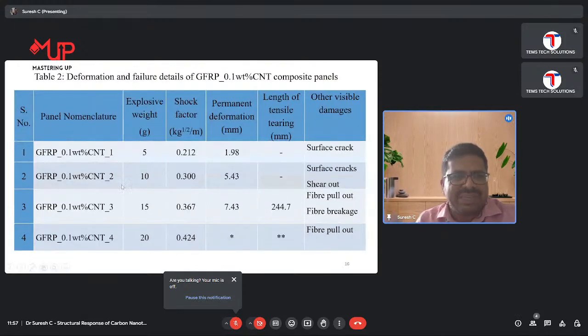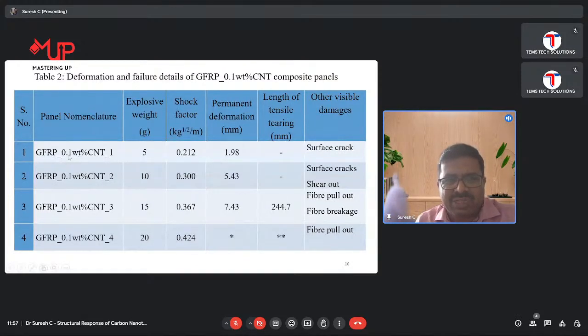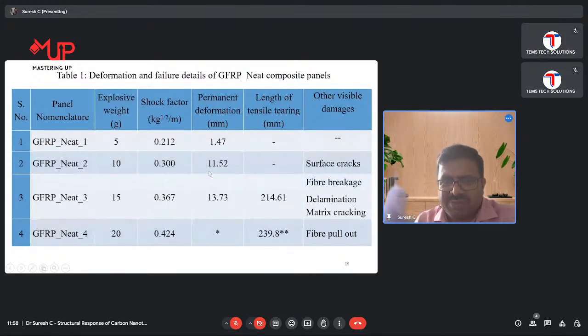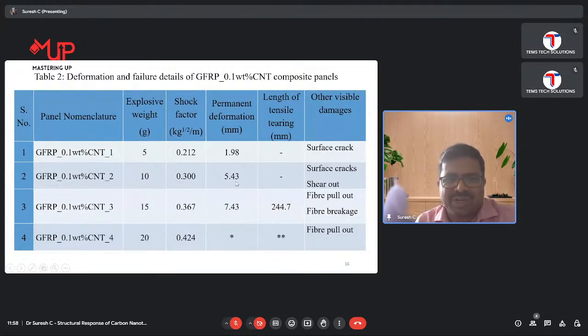Same when we continued with 0.1 weight percentage of carbon nanotubes for 5, 10, 15, and 20 grams, these are the damages happening on the structure. Here you can see in the previous case for 10 gram the deformation is almost 11.52, but here it has reduced to 5.43 because of adding CNT. It has given strength to the composites and reduced the deformation happening on the composites.